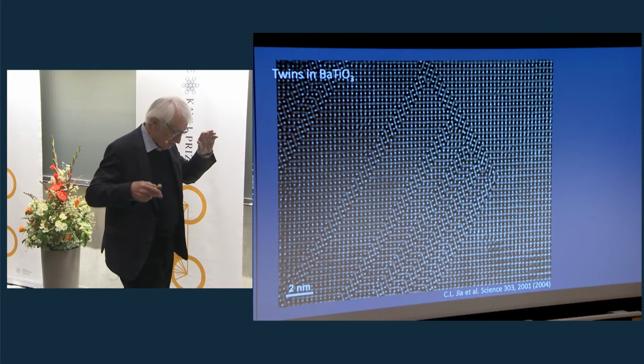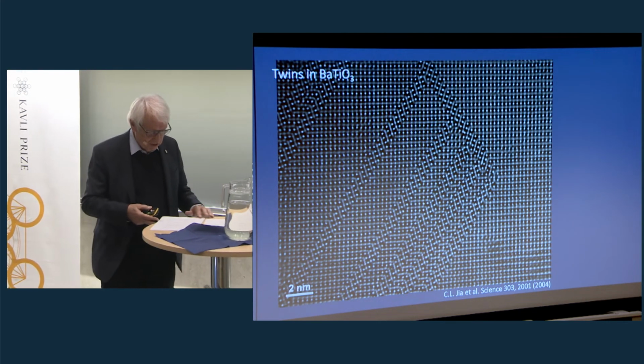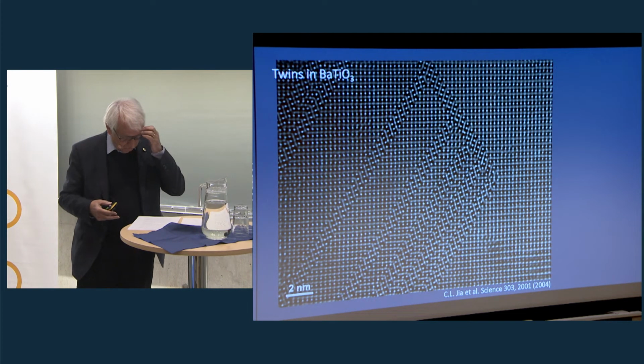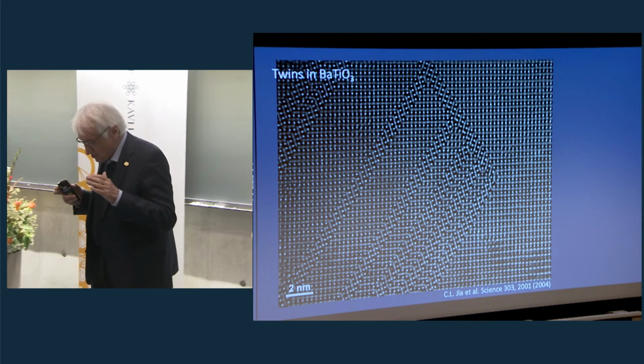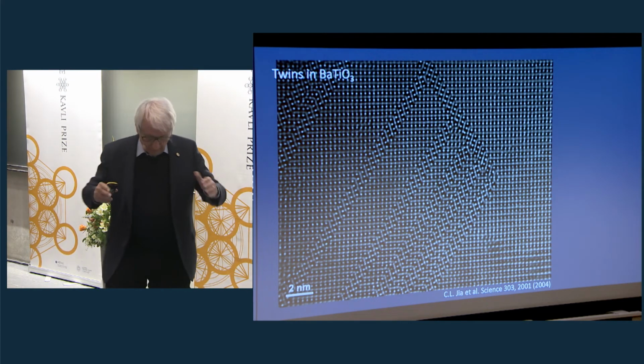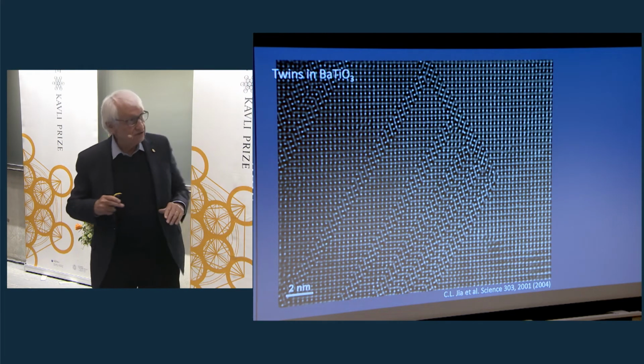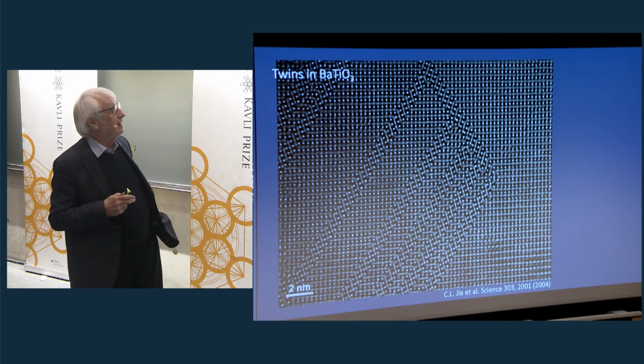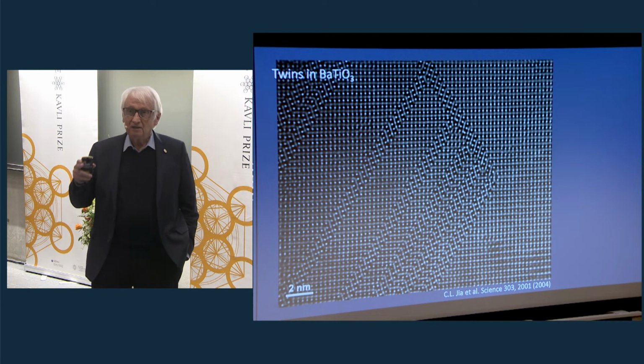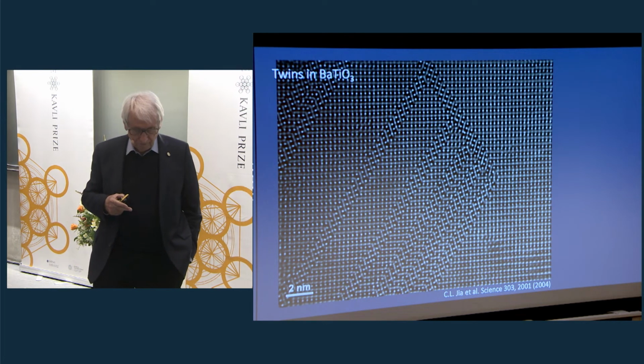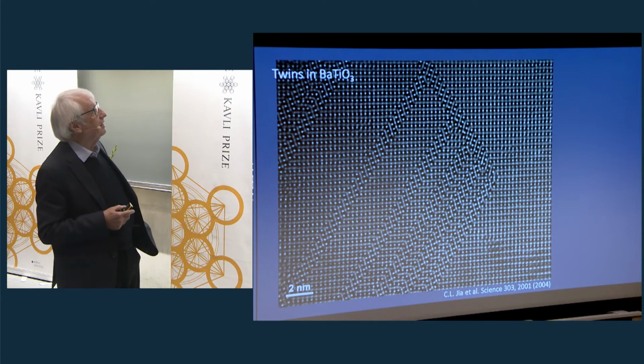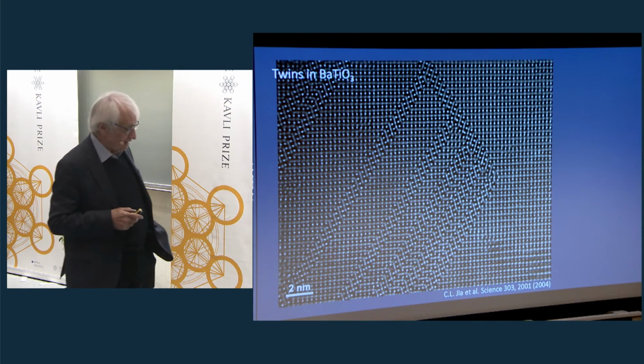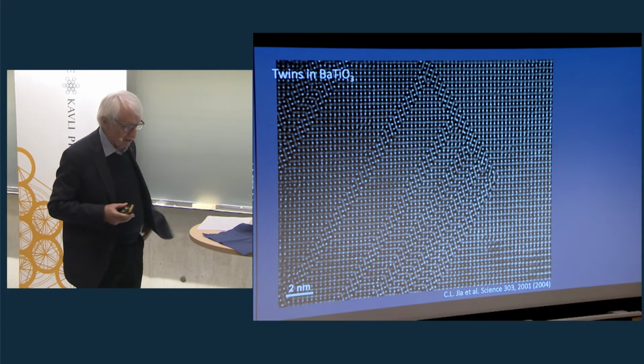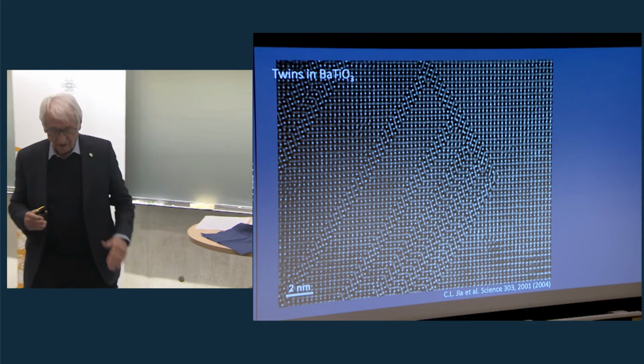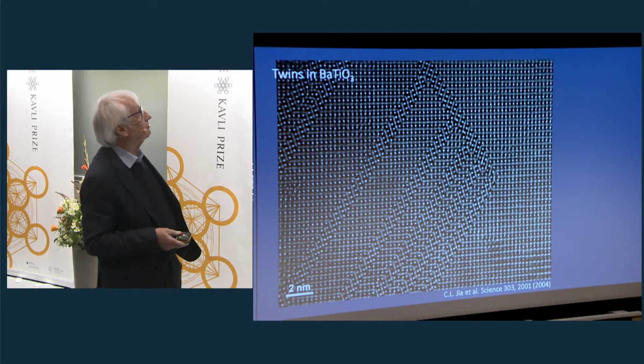People had a lot of discussions about this for some years, and many ideas were put forward. And one of them was that the thin film layers would show a twin structure, and inside the twin structure, the stoichiometry of the layers of the films was disturbed, and it was postulated that you have less oxygen there. That means under-stoichiometric oxygen concentration.